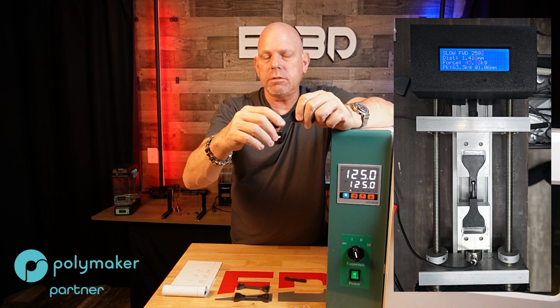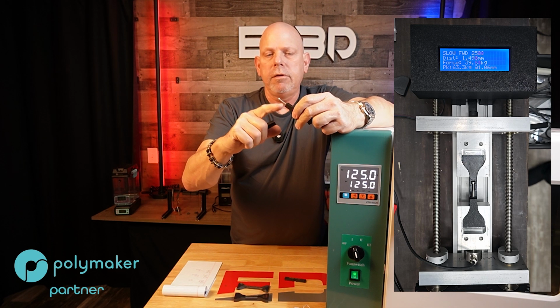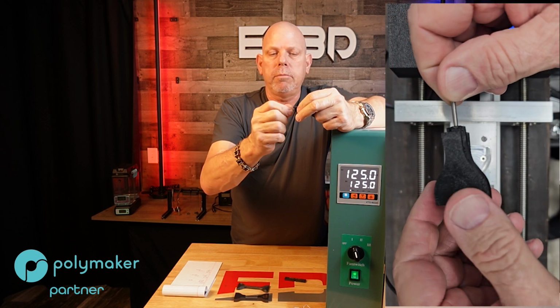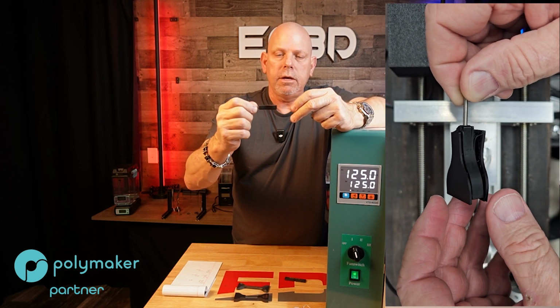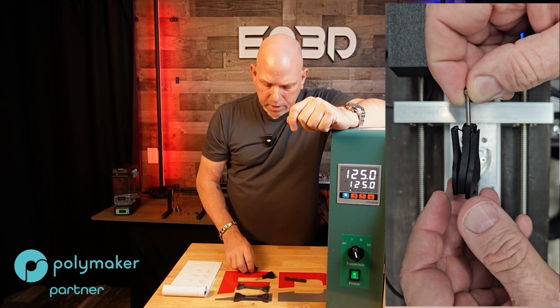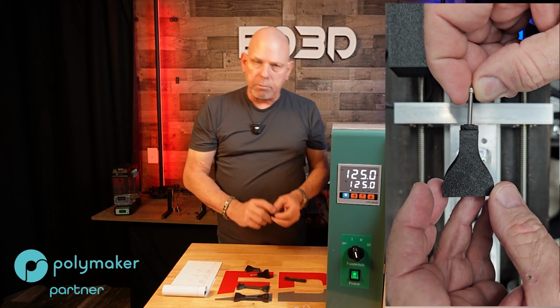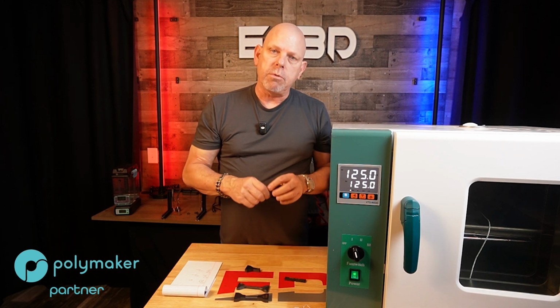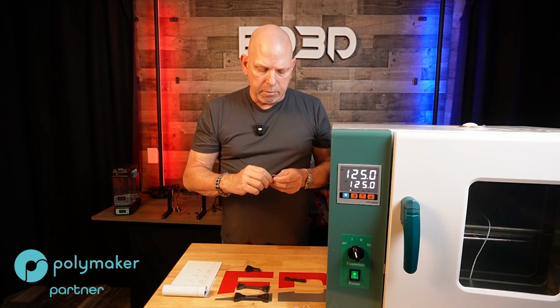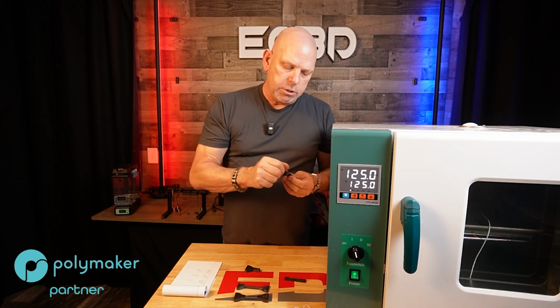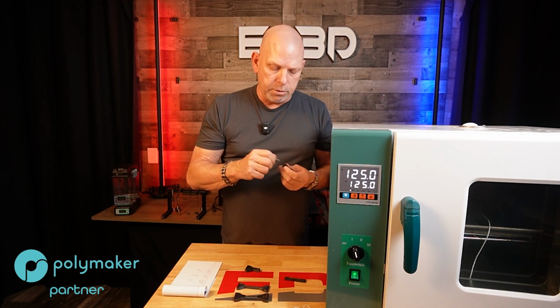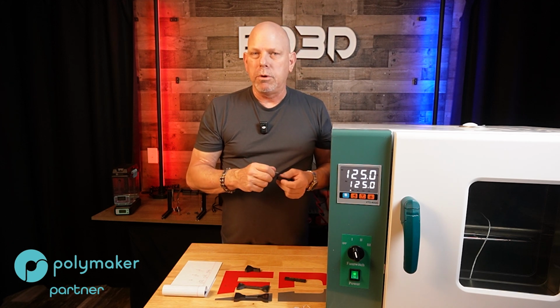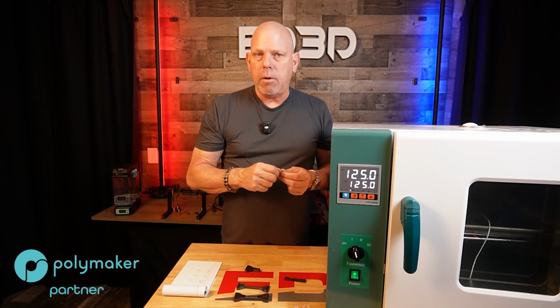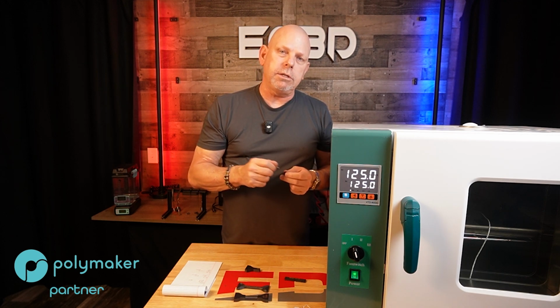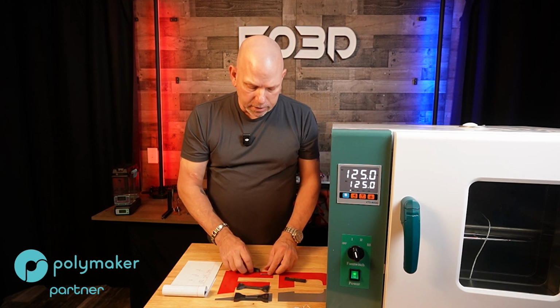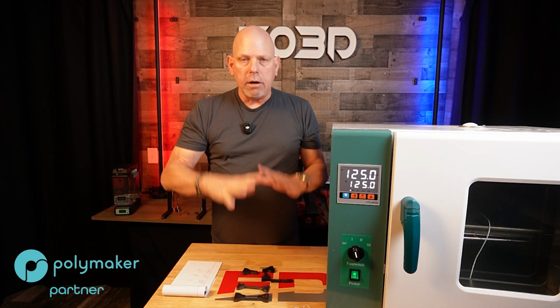I've done a couple of test pulls so far, and surprisingly enough, the heat set didn't fail, the print itself failed, and basically the core broke out of the top and the bottom, and it just basically pulled it apart. So I'm going to be playing around with that, and then I'm also printing a set of these where they're going to be direct thread. Now, PPS carbon fiber, probably not going to be just screwing a screw down in there, because the stuff is so brittle it'll probably shatter. So I might wind up using a tap and tapping it and then threading direct into it and pulling it, but time will tell on that. So that's where we're headed with the machine testing.